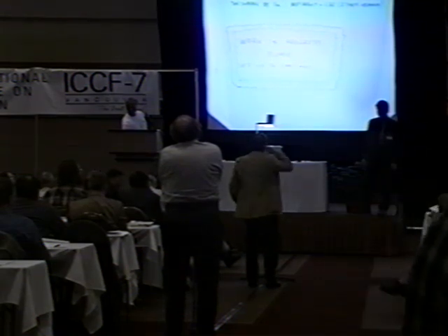Frank? Yes, Michael Schaefer, General Atomics, USA. This is a question about technique, really. It seems to me that you are trying to optimize loading as determined by the resistance ratio. And my question is, you are pulsing this palladium wire through very large current pulses which yield very large temperature cycling. Wouldn't this lead to damage to your palladium, and therefore the resistance might be a measure more of damage than of loading?